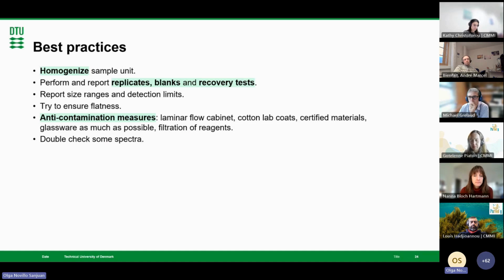So you can also perform and report your replicates, and make blanks periodically, so you can remove these blanks from your samples, or apply the appropriate statistical approach. Always try to do a recovery test, because it will give your method a lot of robustness and credibility. And for publishing, it's really nice for all of us to read how it was actually done, and to avoid misinterpretations of the data.